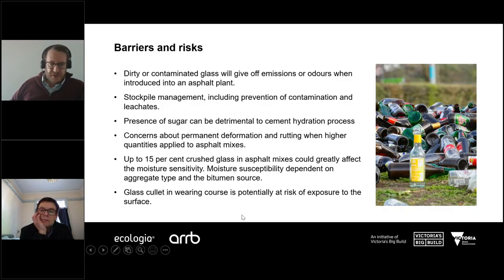There's also the potential that we could be affecting the moisture sensitivity, and that's again down to potential contaminants, but also potentially down to the slightly smoother surface of recycled crushed glass in comparison to natural aggregates. So we just need to be mindful there, and obviously that's going to be dependent on what combination of aggregate type is also being incorporated into the asphalt mixture, and also potentially on the bitumen source.